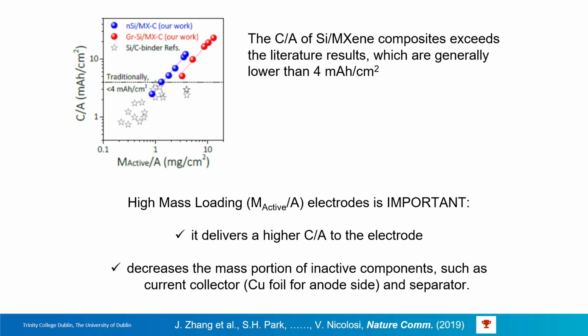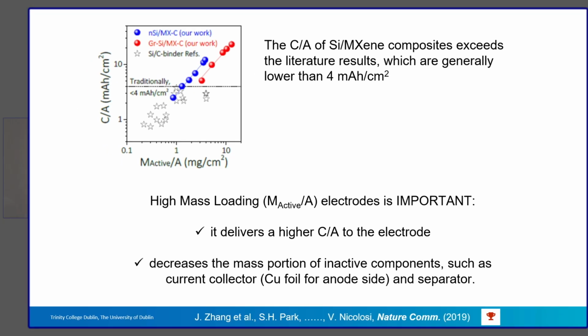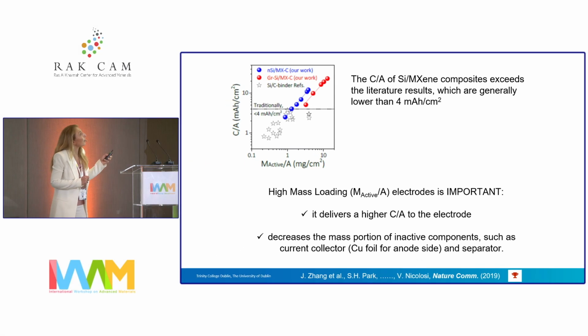This is pretty much the highlight of this type of work, where if you look at the areal capacity as a function of the mass loading here, what we get is traditionally, this is the bottleneck that you normally face, around 4 milliamp hours per centimeter square, while our work goes substantially above. So you go way beyond this threshold.